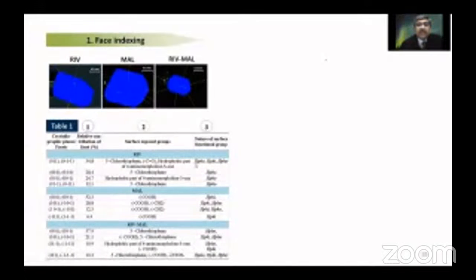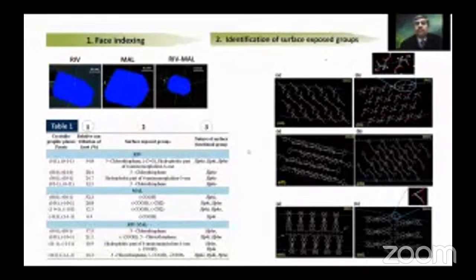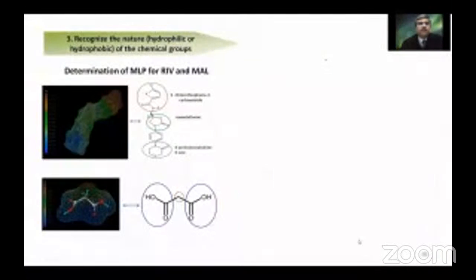Were they hydrophobic in nature? HPHO denotes hydrophobicity, while HPHI stands for hydrophilic groups. And this was done for rivaroxaban, malonic acid, and the riv-mal co-crystal. We also identified the groups that were exposed on the surface using the Mercury software and looking at their crystallographic information file. What are the groups that are exposed on the surfaces of the samples? So this is for rivaroxaban, this is for malonic acid, and this is for the co-crystal.